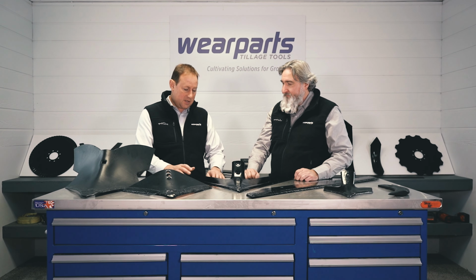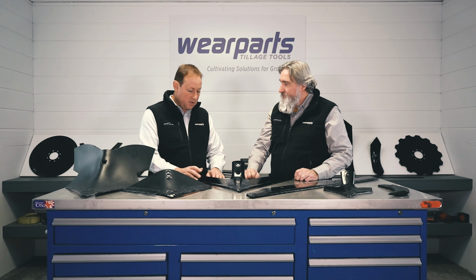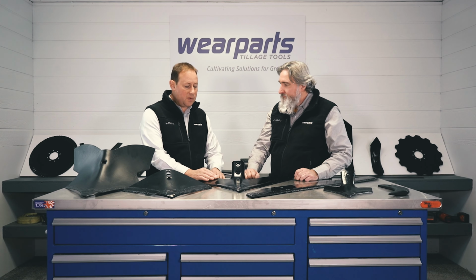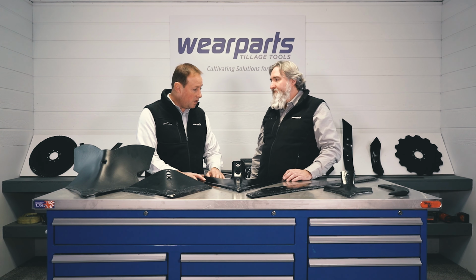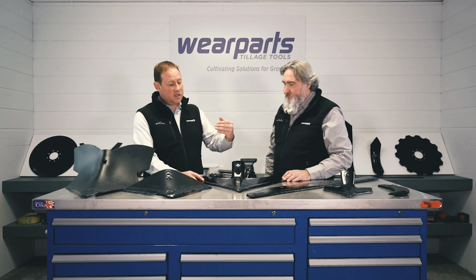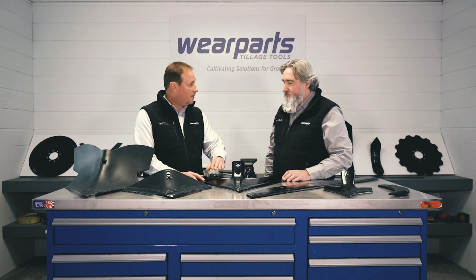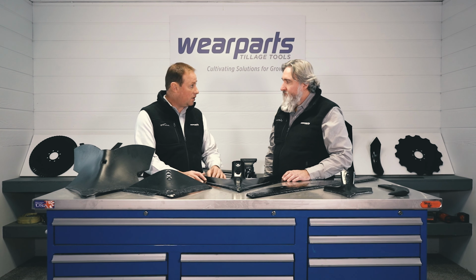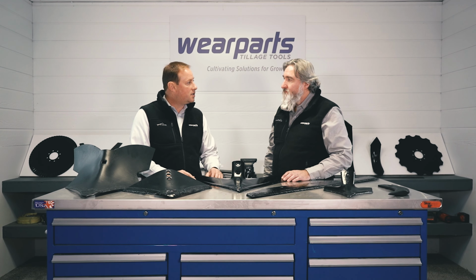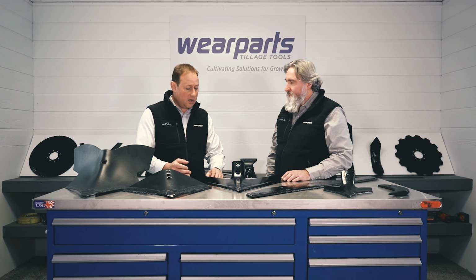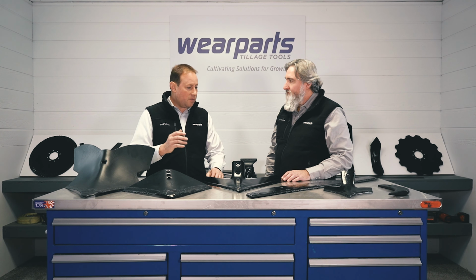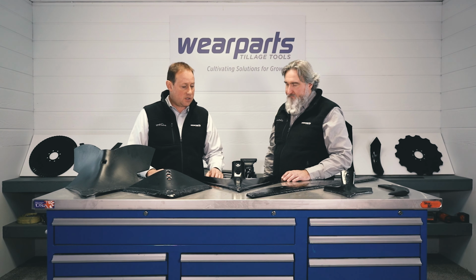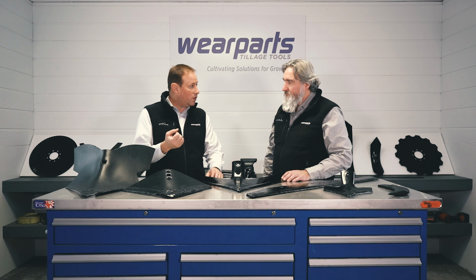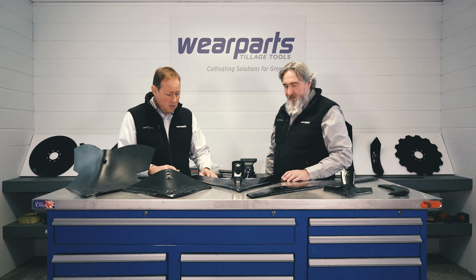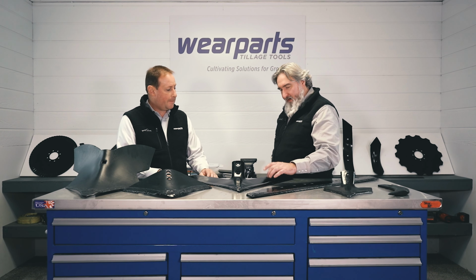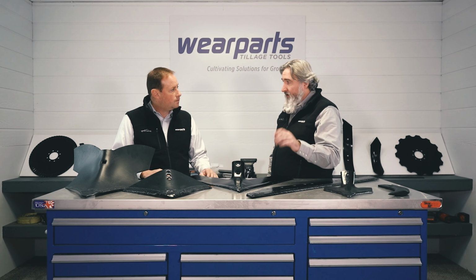And we've done testing on the base material, like this boron steel sweep here is 48 to 52 Rockwell. Before we start, we take this back to the lab and we test the hardness of the base material, and after the hard facing it hasn't changed. It's still at that 48 to 52. Whereas on other methods, when you're running that heat so much higher, it actually pulls some of that tempering out. You end up with softer spots in that base material that are going to actually wear out faster.